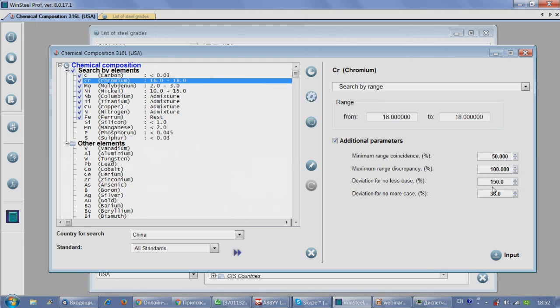By default, 150%. So if aluminum content is more than 0.02, it will be the minimum content. At maximum will be 0.03. So we should multiply this minimum content by 1.5 or 150% to get the maximum value of these elements. I think you understand that, and the same algorithm is used for search by composition, because